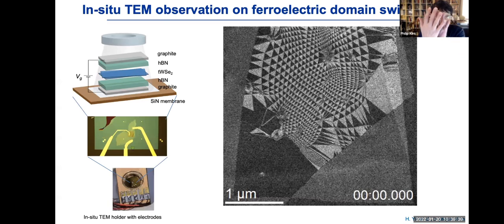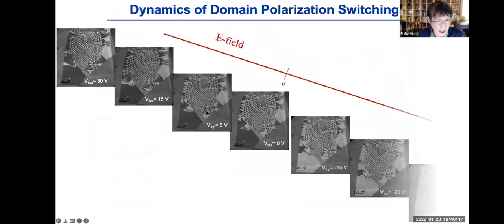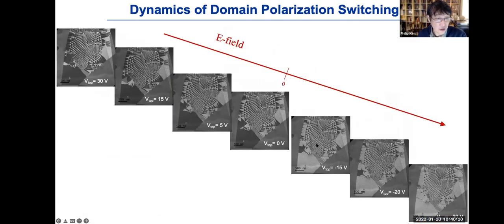I'm showing here layers put together with a small twisting angle, right? We put this sample under the TEM grid, and we apply the electric field in the vertical direction. As I briefly mentioned, for this TMD layer, the dark part and bright part correspond to opposite domains, with the opposite direction of polarization developed. So you can view this as if there is an interesting ferroelectric domain structure tied together. And not surprisingly, when you apply the electric field, you can start to see the control of those domain structures and sizes, and sometimes large-scale domain reversal happening.